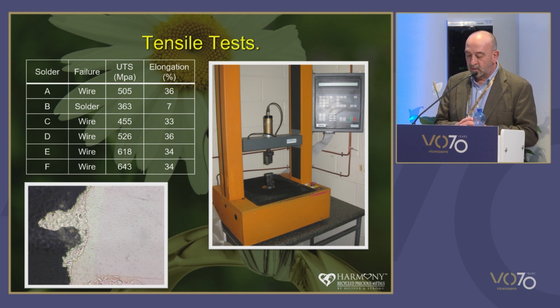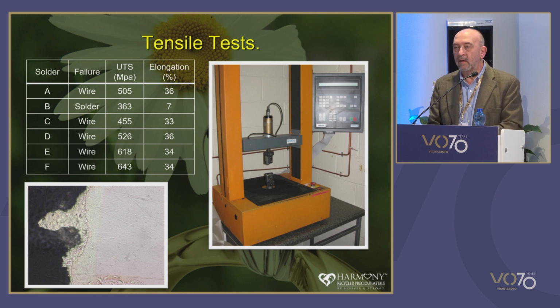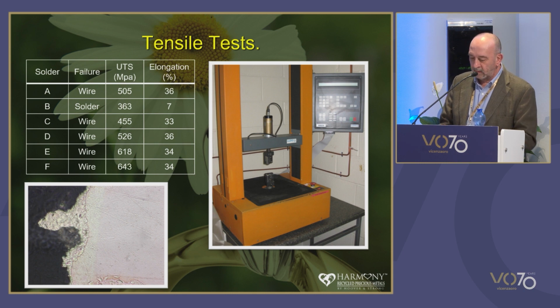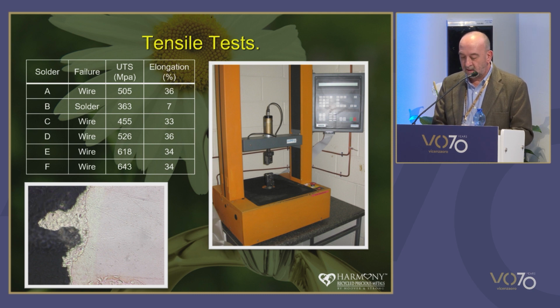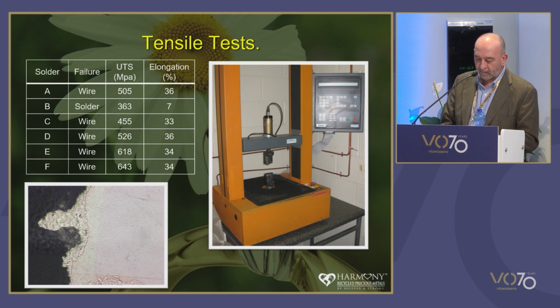The tensile strength that was recorded at 363 megapascals, or newtons per millimeter squared, is adequate for most jewellery applications, so there's not necessarily any need to worry about this. It's just not as good as the others in the test. And the results would suggest that mechanical properties of the solder have been compromised due to design considerations to achieve the desired melt range and the desired colour.